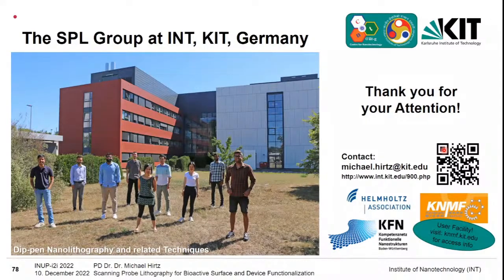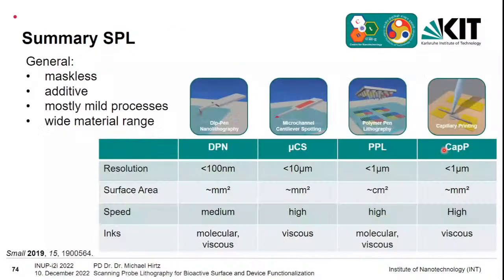That's a very good question. This is really dependent on the ink itself. In the case of dip pen nanolithography, for example, if you have these thiol patterns, or, I didn't show that, but you can also have click chemistry patterns, then you covalently bind to the surface, and these patterns are very stable. You can do washing with them, you can do whatever that does not destroy the whole surface, and they will be stable. If you have things like the phospholipids that I showed, they are just physisorbed to the surface. So they're really just lying on the surface.